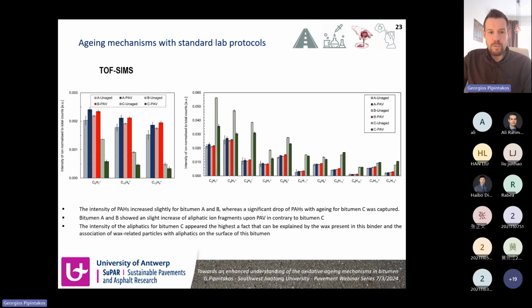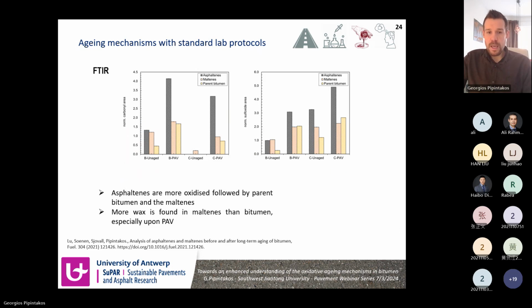Moreover, other chemical compounds like polycyclic aromatic hydrocarbons were increased with aging for bitumen A and B. And we also had a slight increase of aliphatic ions, whereas the intensity of aliphatics was the highest for bitumen C, which I recall was the waxy bitumen. And again, an association between the wax-related particles and aliphatics can be found. And later this was used also for microscopic purposes.